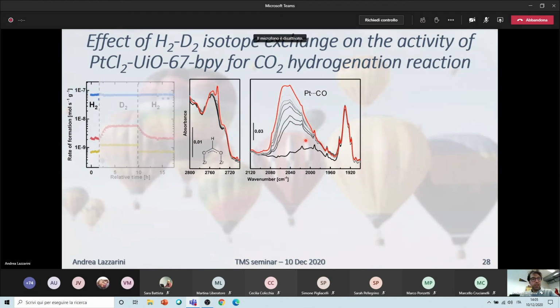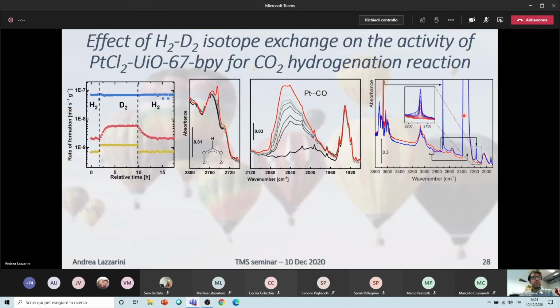But then when we exchanged the feed with deuterium, we observed a dramatic increase in the methanol production. And the explanation that we gave was that we were basically increasing the amount of this formate species. As you can see, this very tiny signal that was here is shifting because deuterium is heavier, so it's shifting the signal to lower energies, and you see the intensity of the signal is hundreds of times more intense. That is justifying the increase of the production of methanol.